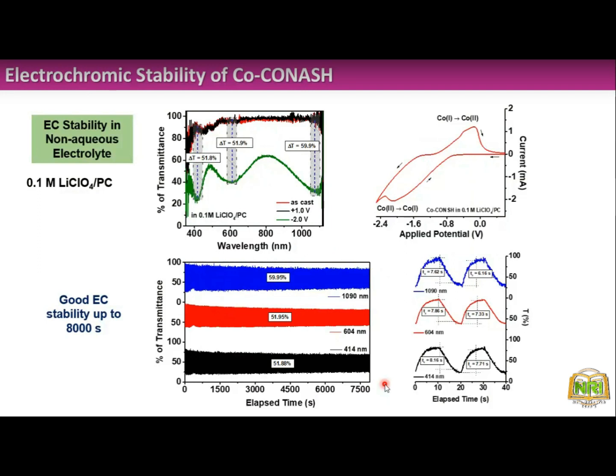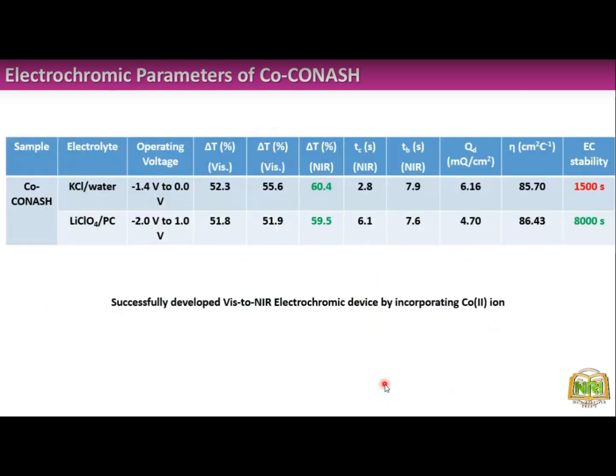So ultimately these are the parameters. In KCl water we have checked that it is stable up to 1,500 seconds. Beyond that, due to the hydrogen evolution reaction, the compound is getting spoiled. But in non-aqueous solution, it is up to 8000 seconds. The compound is very stable. At the same time, it includes the visible region also. It is showing NIR modulation. That means it can block both visible as well as NIR radiation.